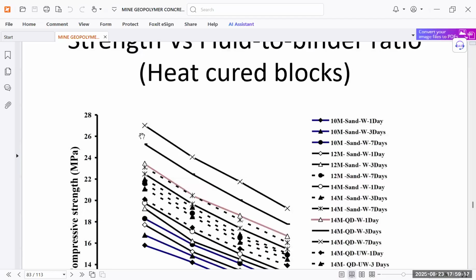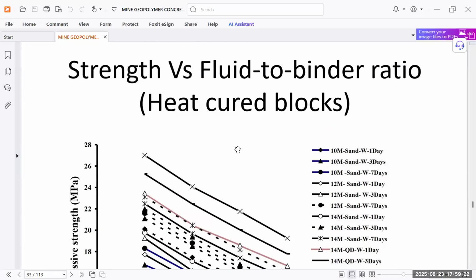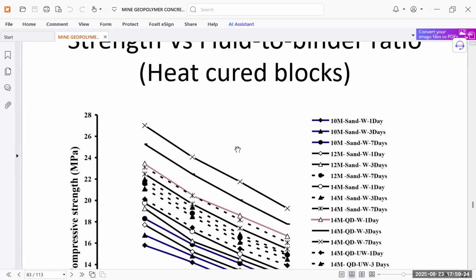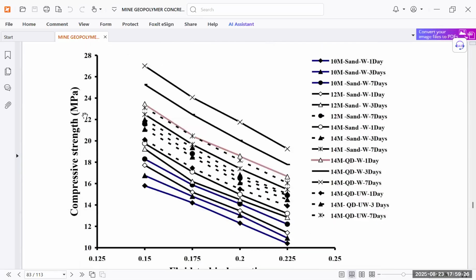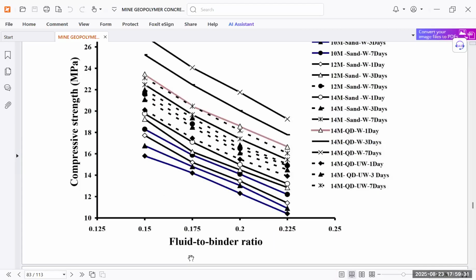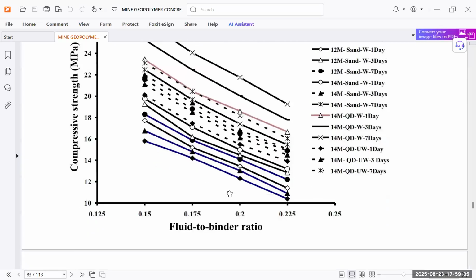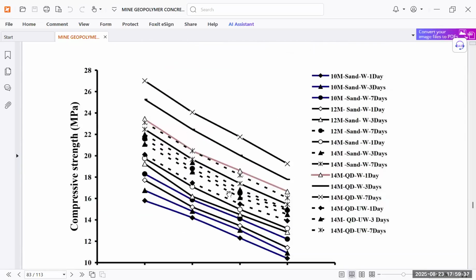In the same way, you can get those graphs as in the case of the cement concrete which we have done. So you can see these results. The strength is changing as per the requirement, and this is the fluid to binder ratio that is being changed. Whatever we are achieving in concrete, we can achieve here also using the fluid to binder ratio. So we are getting similar things, which we used to obtain in the case of cement concrete, without cement.